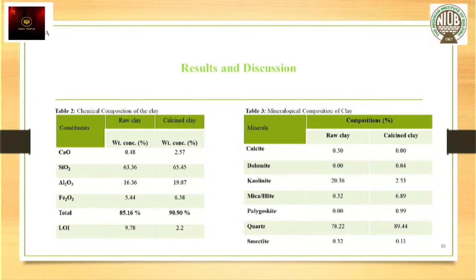which you can see that the mineral quartz is the predominant compound in both the raw clay and the calcined clay, followed by the kaolinite. And from the results, it shows that the clay material used for the production of the pozzolana is kaolinitic.